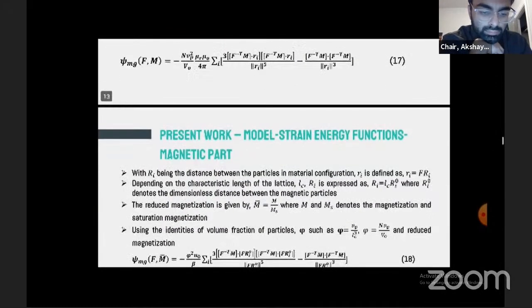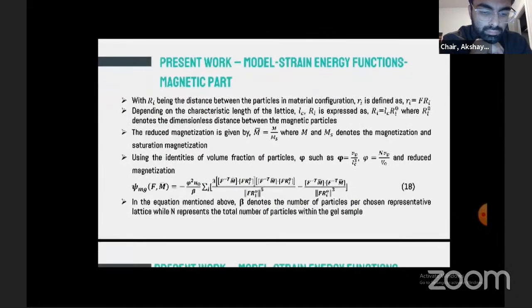Further, bringing in information like capital R being the distance between the particles in the material configuration, it is rewritten to bring in the relationship of the distance between the particles in the spatial and the material configuration as small r equal to F times capital R. The reduced magnetization term is used to simplify equation 17. So m bar is the ratio of magnetization and the saturation magnetization. Using these identities, equation 17 is further reduced, where beta denotes the number of particles per chosen representative lattice, while N represents the total number of particles within the gel sample.